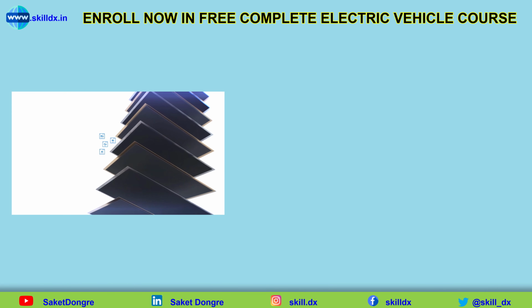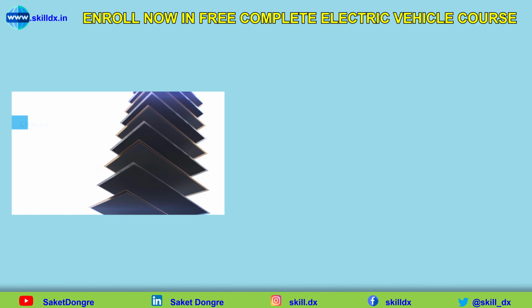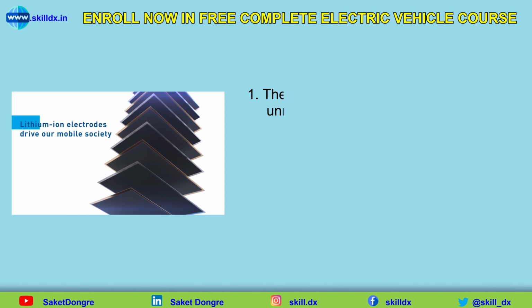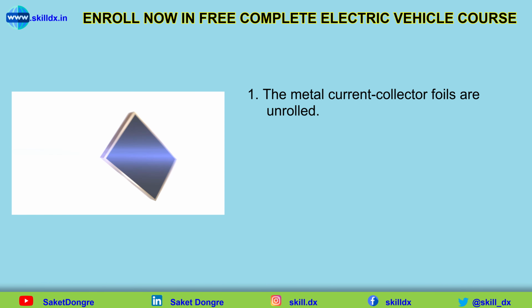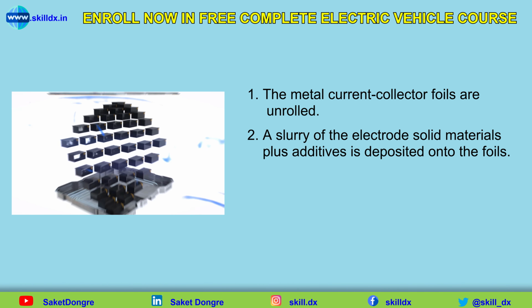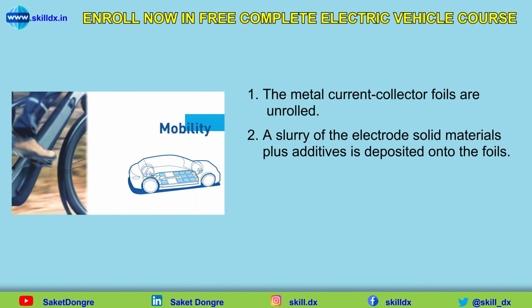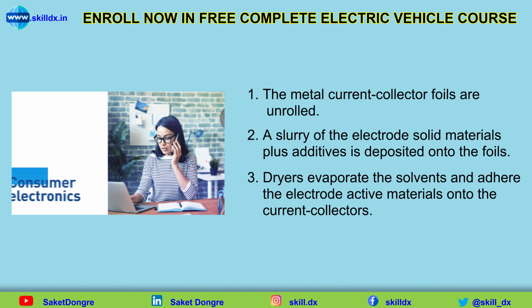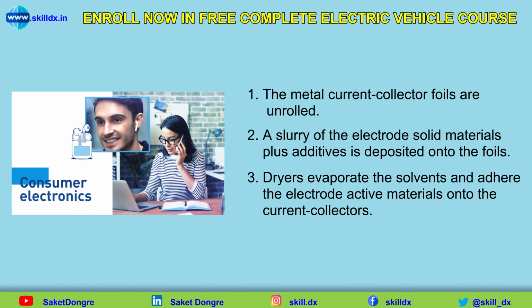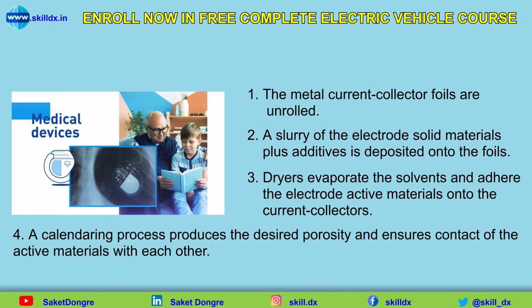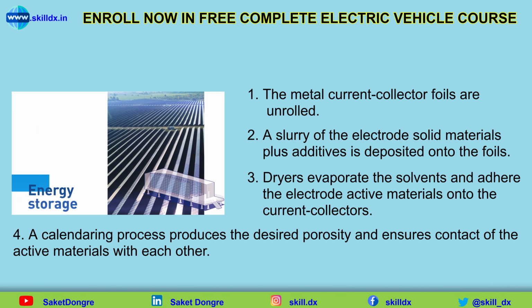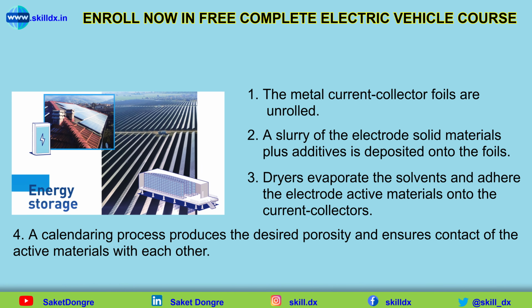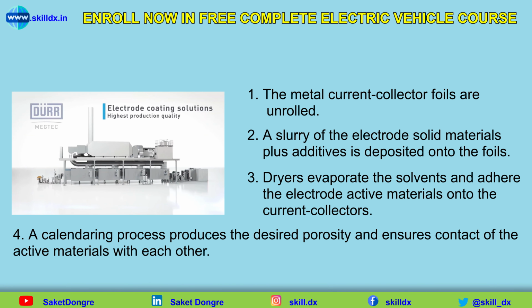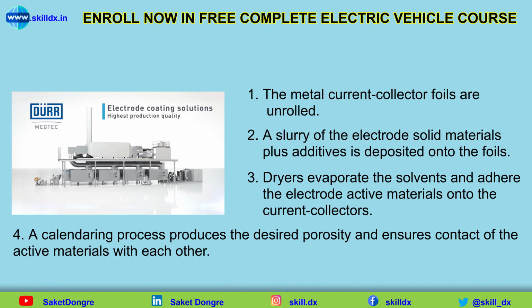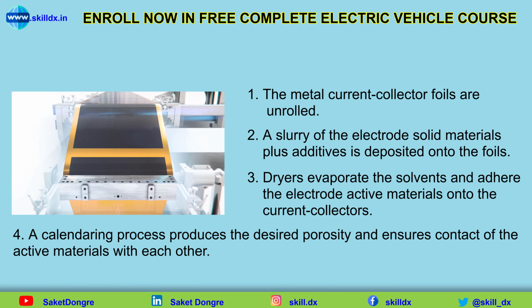At this point in discussing how the lithium cell battery is fabricated, we have seen how the electrodes are fabricated. The metal current collector foils are unrolled. A slurry of the electrode solid material plus additives is deposited onto the foil. Dryers evaporate the solvent and adhere the electrode active materials onto the current collectors. A calendering process produces the desired porosity and ensures contact of the active materials with each other. And finally, the electrodes are slit to their final widths, and the narrower electrode foils are re-reeled in preparation for the next step of cell manufacturing.